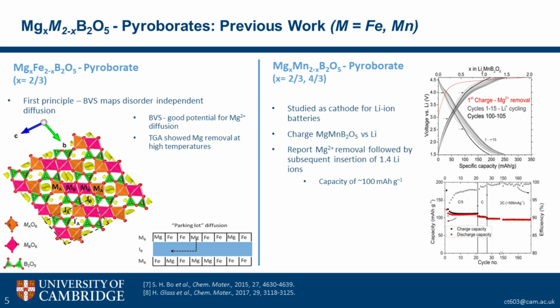And they discovered that there was this parking lot diffusion mechanism where the magnesium could hop out into these channels and move through them, not caring about the site disorder that you have in these crystal sites. They also did some TGA, and they saw that magnesium was being removed from the structure at high temperatures. And then we've got this other work done on the magnesium-manganese pyroborate system.